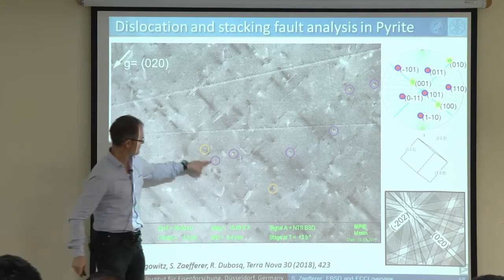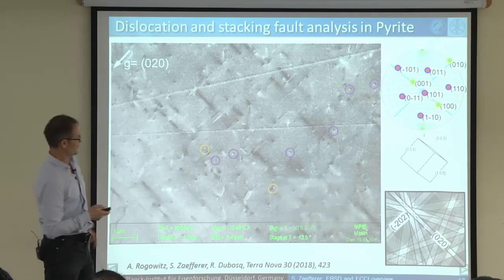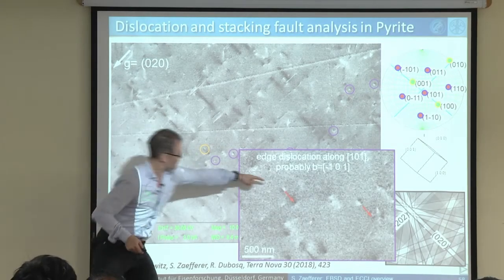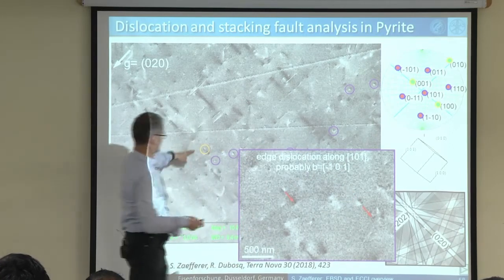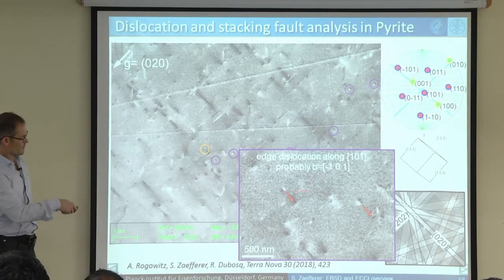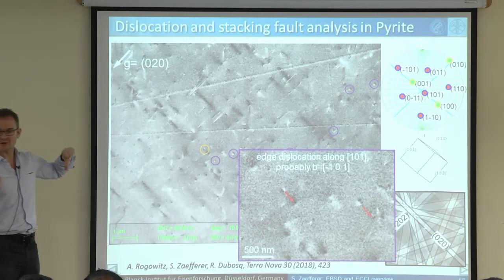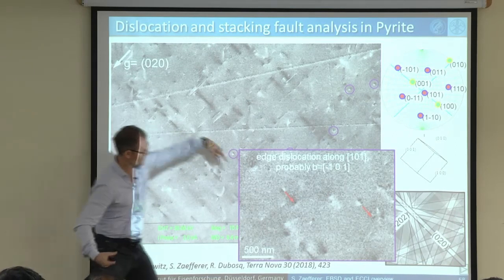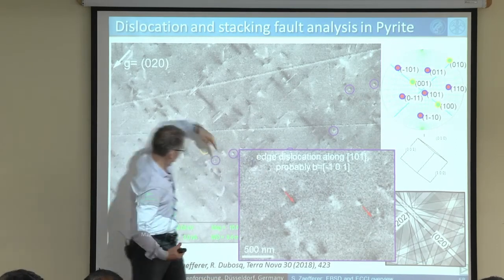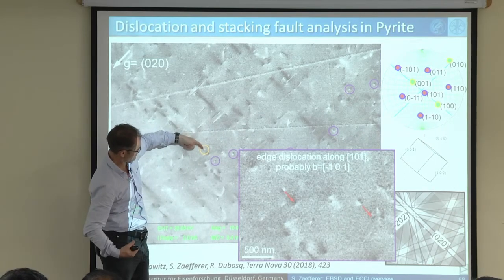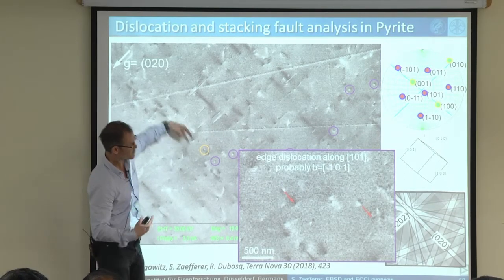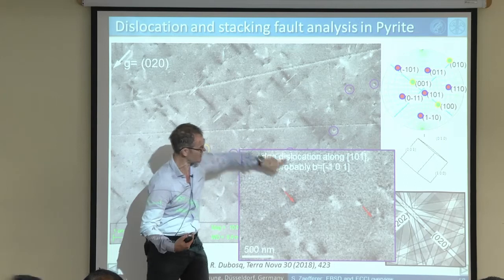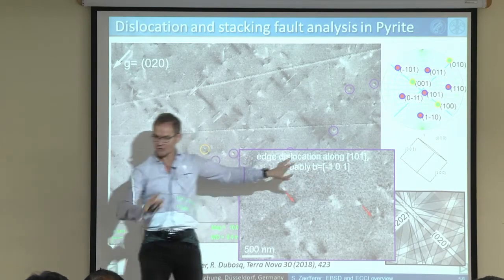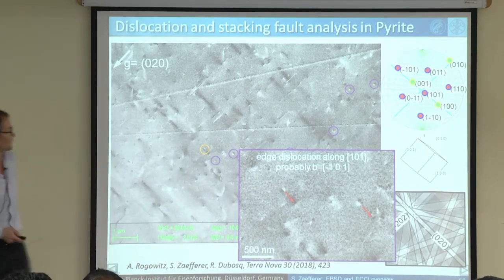So you see first these dislocations here. If we zoom in, they always have a white side and a dark side and a white side. And like that you can actually separate. And actually you can, by calculation, show that the Burgers vector is then parallel to or perpendicular to the contrast change from white to black. And we know what kind of direction is there. We know that it's a 101 direction, so we can tell what kind of Burgers vector we have there.